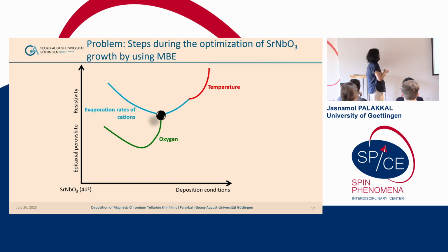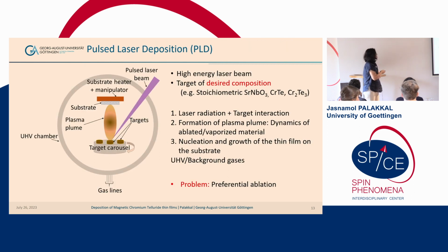So this is one example of the steps that I took until I finished optimizing the growth of an oxide material, SrNbO3. Each step took at least 3 months for final optimization. So this is the main problem, and in such cases, if you are directly growing such a material, it's easy and convenient to use pulsed laser deposition.